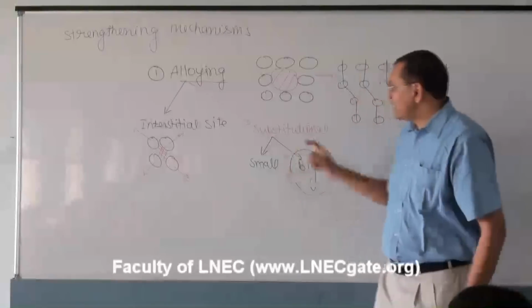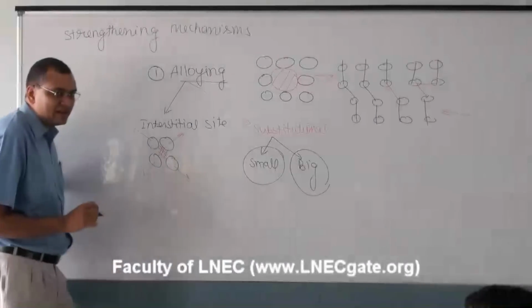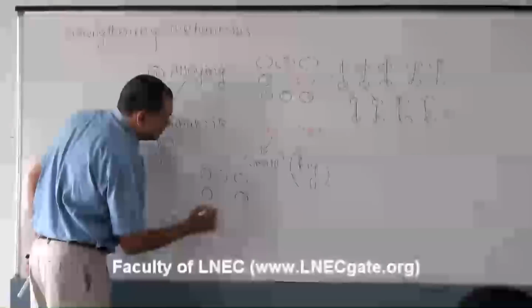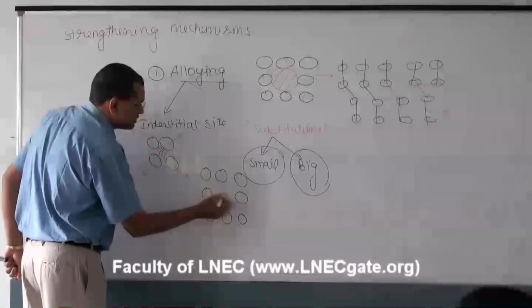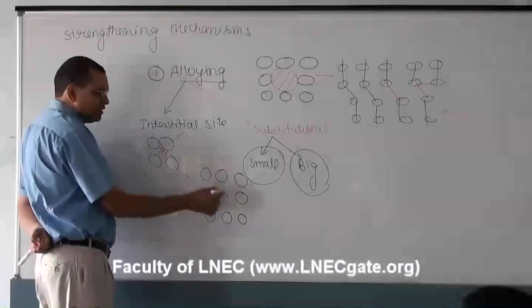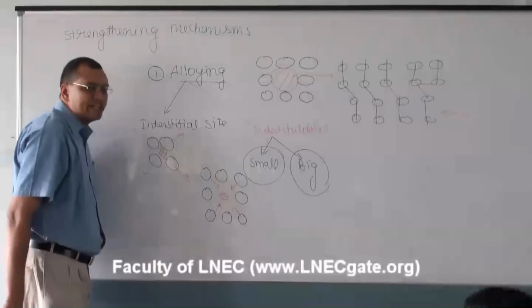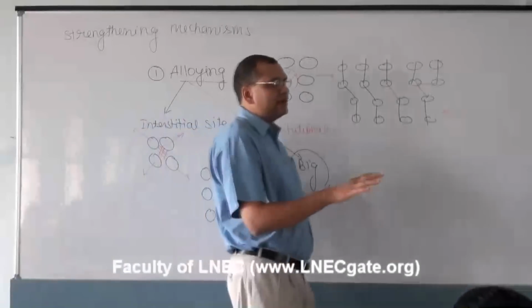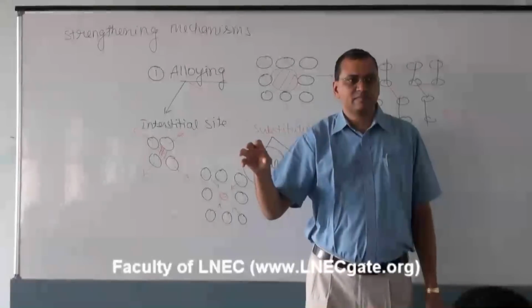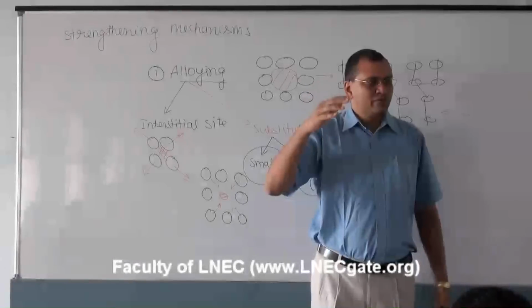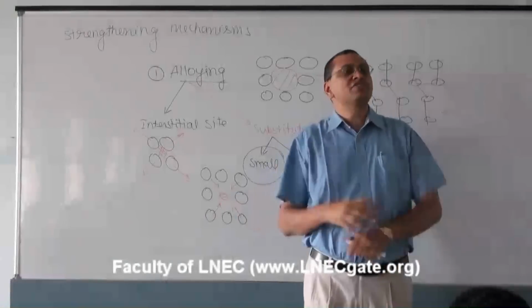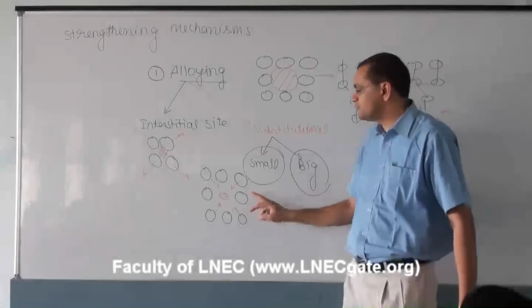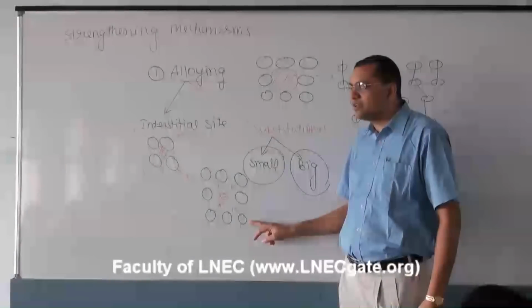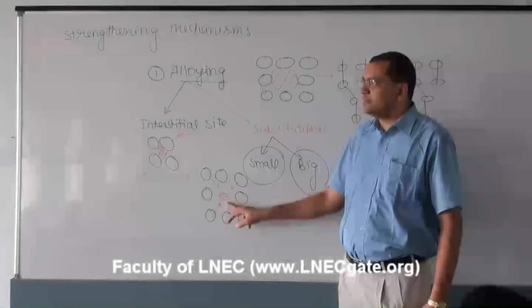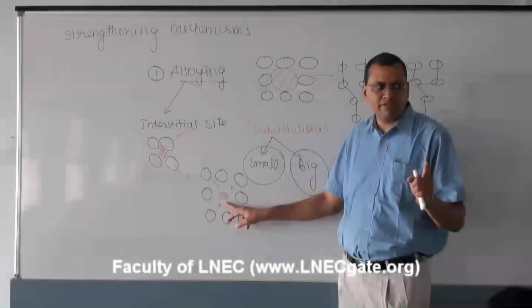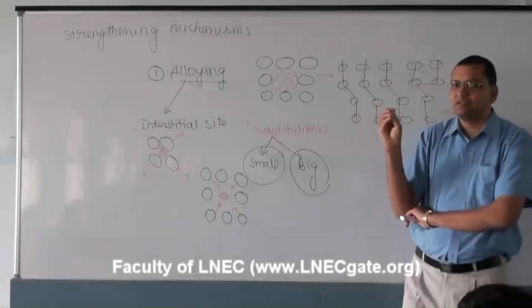Is that clear? And let us say when the substitutional impurity size is smaller than the host atoms, there will be some extra space created. So these host atoms will try to occupy that position. For example, there are bricks which are kept one over another without cement. Somewhere from the middle, take out one brick. Whatever space has been created, the bricks will try to occupy that position. Same thing will happen with the atoms. So these atoms will experience a tensile strain field. A small size impurity atom produces a tensile strain field. A large size impurity atom produces a compressive strain field.